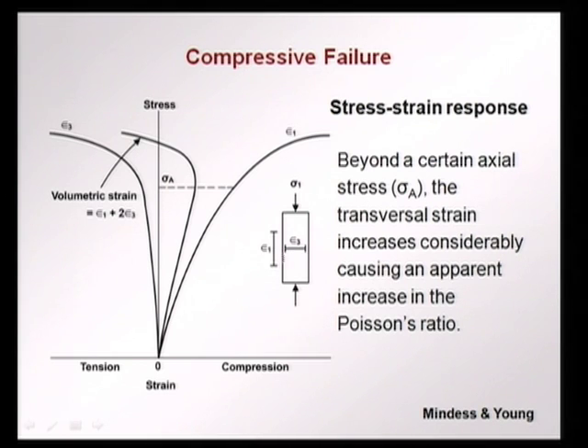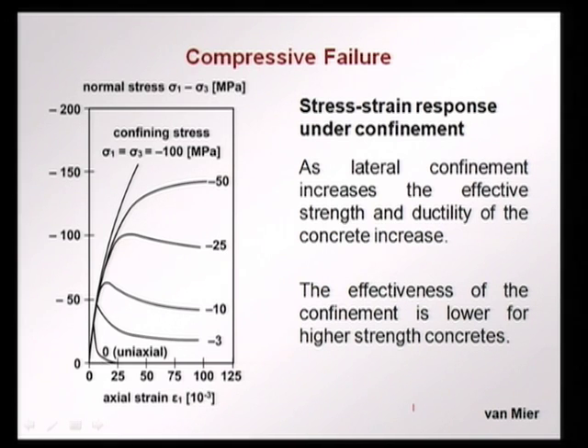If we can stop the lateral expansion from occurring, then we can increase the effective load carrying capacity of the element, and this is where stirrups and ties that we use in compression come in handy. We can understand this better when we look at the effect of confining stress on the normal stress and axial strain behavior. So, these are graphs from the book of van Mier showing the normal stress versus the axial strain for different confining stresses. If you do not have any confining stress, this would be the stress strain behavior, failure occurring at an axial stress of say about 30 megapascal. The same concrete now with about 3 megapascal confining stress goes from here to here, 10 megapascal, 25, 50, 100.